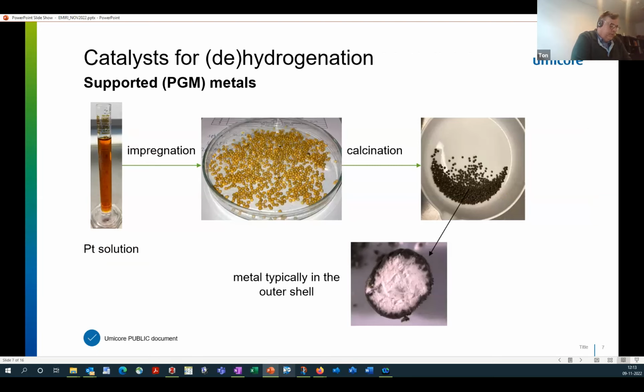So to release the hydrogen, we need a catalyst, and catalysts are actually well known. These are dehydrogenation reactions, and noble metals are supported. Noble metals like platinum, palladium, ruthenium, rhodium will work for this reaction. So to make a catalyst, you start off with a solution of a platinum salt, which you impregnate on the support material.